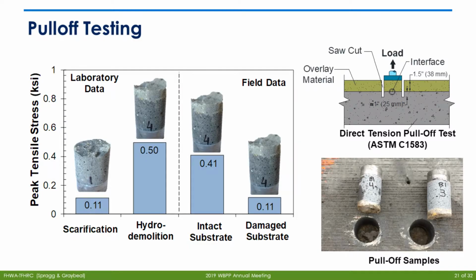You create a partial core and then you attach your pull-off disc, and then you have a pull-off machine that just kind of pulls that disc off. So assuming that you get failure at the interface, which is most of the time, if the glue is good, then you can calculate what your bond strength was.